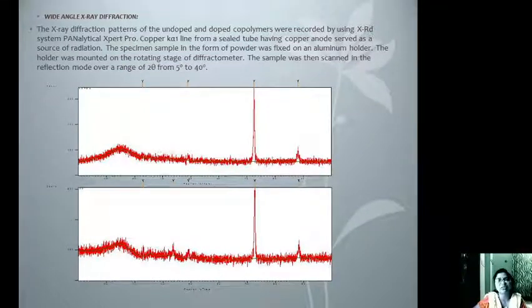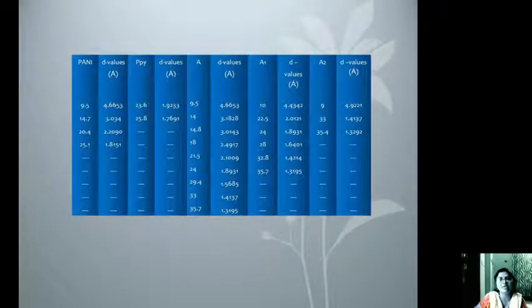Further, the samples were subjected to X-ray diffraction, and the XRD diffractograms of the undoped and the doped samples have been presented here. From the spectra, it is observed that the samples are amorphous in nature. However, small peaks are observed within these regions. We have tabulated the small peaks and their respective d values in Table 3, and from the table it is observed that the self-doped polymer exhibits a large number of peaks as compared to the undoped and